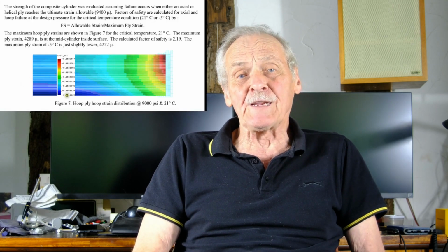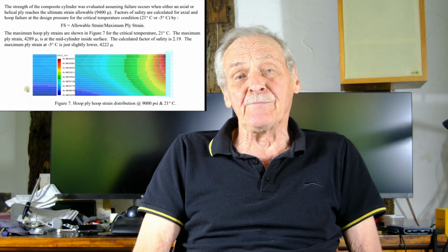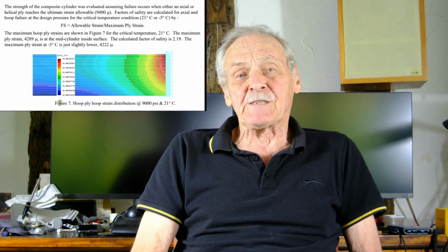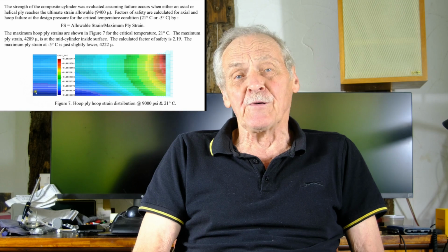So let's look at the results for the carbon fibre hull. Now, what they've done is they've applied an external pressure of 9,000 psi, which corresponds to a dive depth of 6,000 metres, and they've computed the strains at all points through the model. And they've compared this to the estimated failure strain to compute a factor of safety. And if we look at the hoop direction, the highest strains are on the centre line of the hull on the inner surface, the area depicted in blue. And with their definition of factor of safety, they compute 2.19.